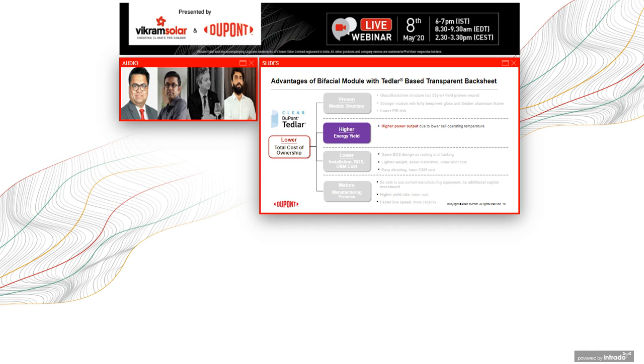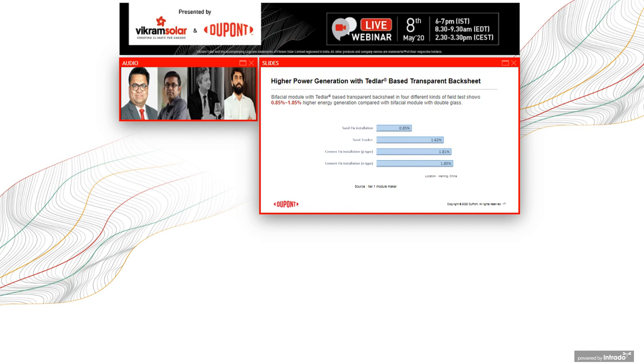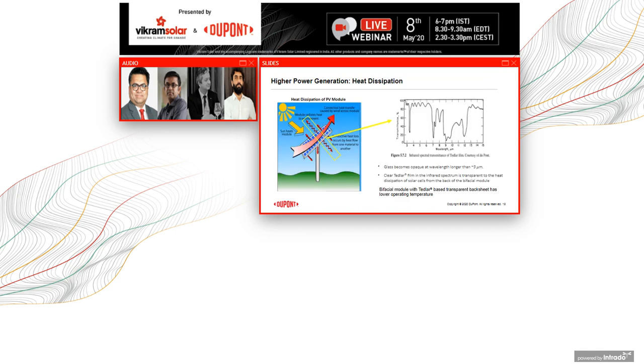So that brings us to the next bucket, the energy yield bucket. I'm showing here some results, again, field results. We always try to go back to the field to prove our point, from a tier 1 module maker. What you see here are 4 different installations: sand fixed installation, sand tracker, and a different surface, a cement with a fixed one, and a cement with a different type of cells. But in all these different tests, over a period of 6 to 8 months, this was done with multiple modules in an array. We see that the bifacial modules with Tedlar transparent backsheets actually outperform. This is the amount of energy gain that you get over glass modules in all these installations.